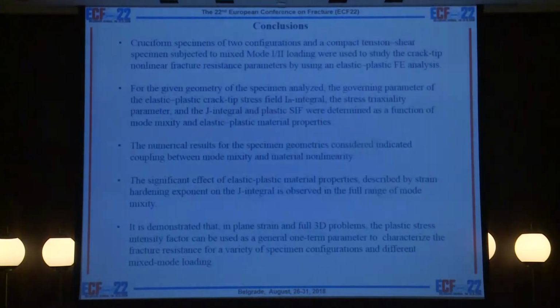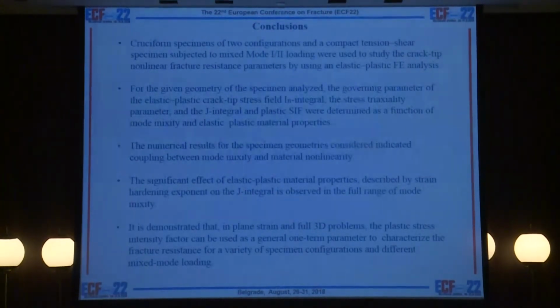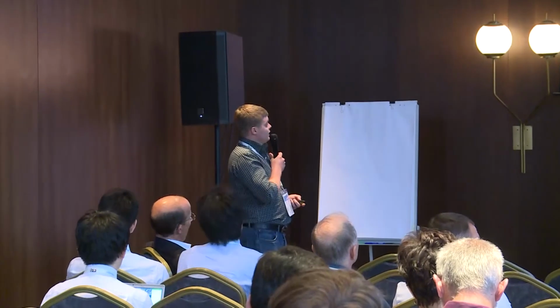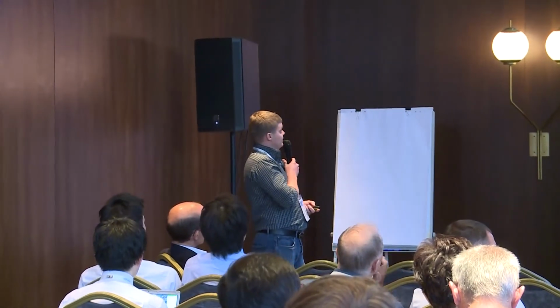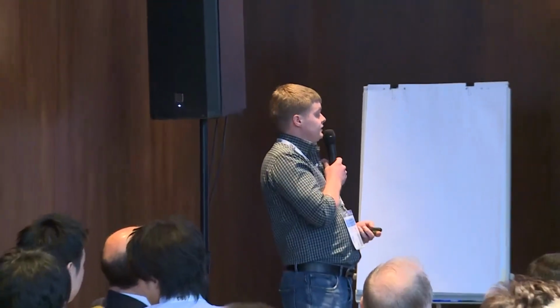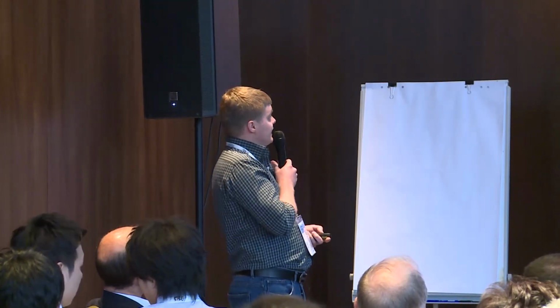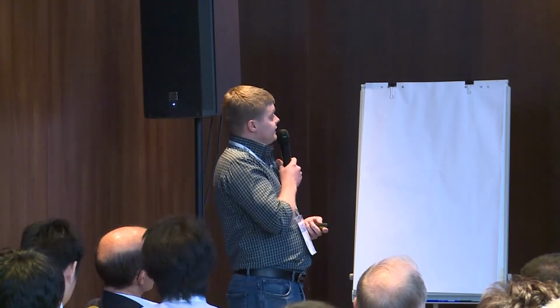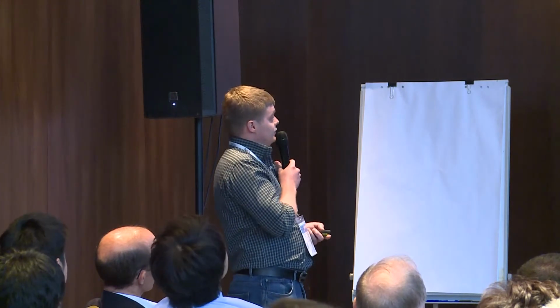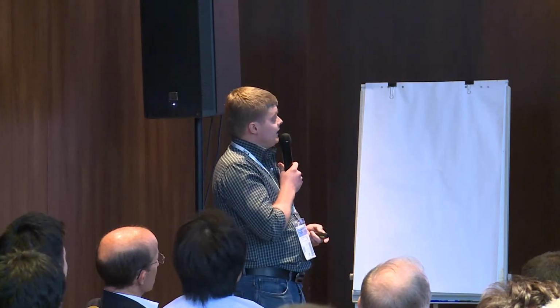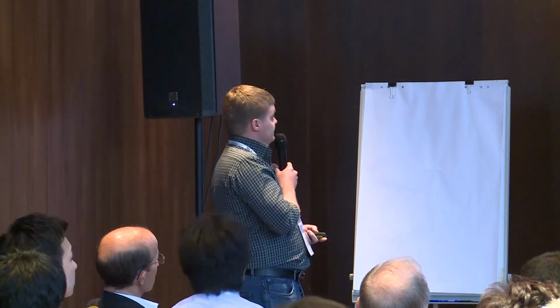So cruciform specimens of two configurations and compact tension shear specimens subjected to mixed mode loading were used to study the crack tip nonlinear fracture resistance parameters by using elastic plastic finite element analysis. For the given geometry of the specimen analyzed, the governing parameter of the elastic plastic crack tip stress field, the IN integral, and the stress triaxiality parameter, the J-integral, and the plastic stress intensity factor were determined as a function of mode mixity and elastic plastic material properties.